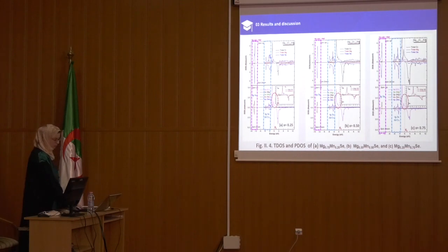The values of the density of states at the Fermi level in the spin-up case are 0.61, 1.13, and 1.86. We note that the contributions from the Se 4p and the Mn 3d states are smaller. As a result, we obtain a half-metallic character, as shown in the figures for the three concentrations, as well as in the density of states.